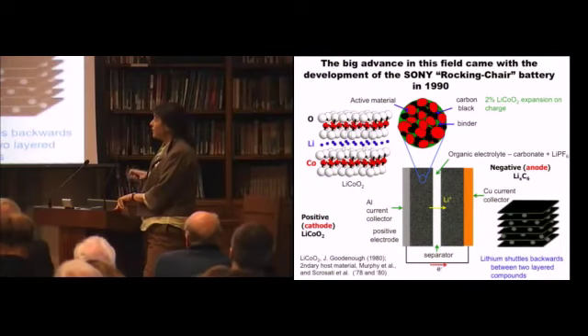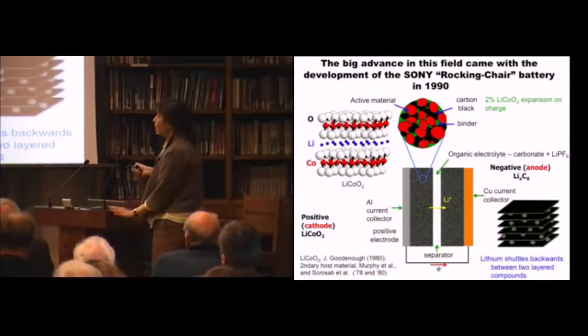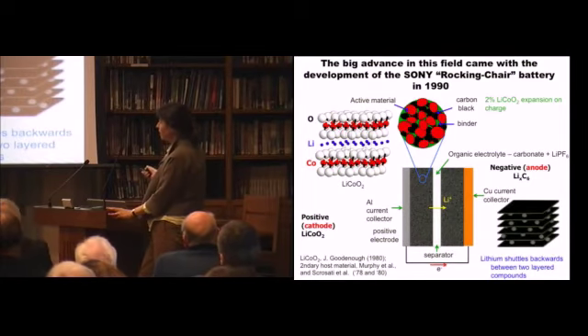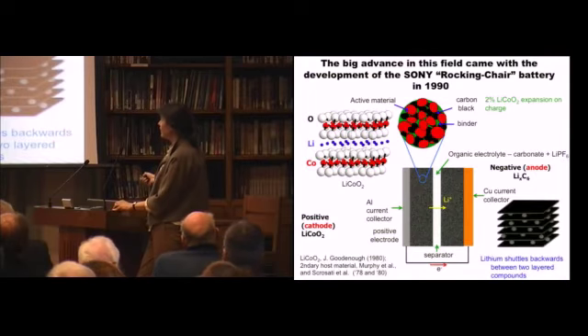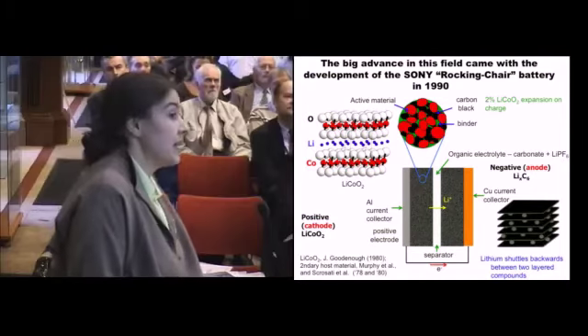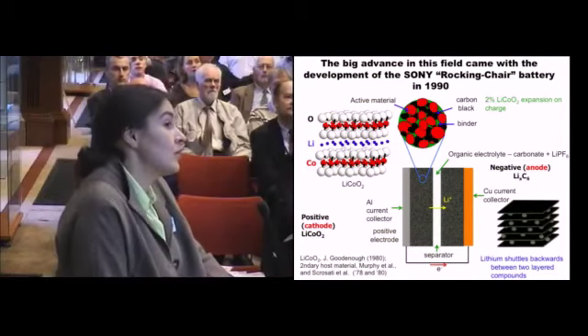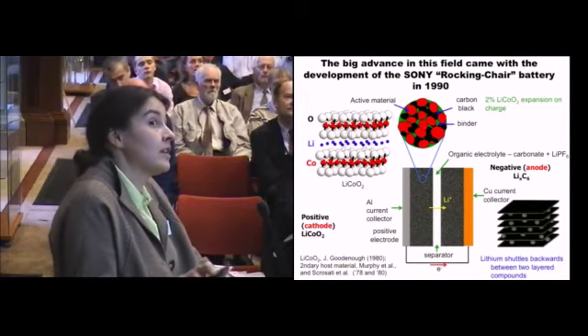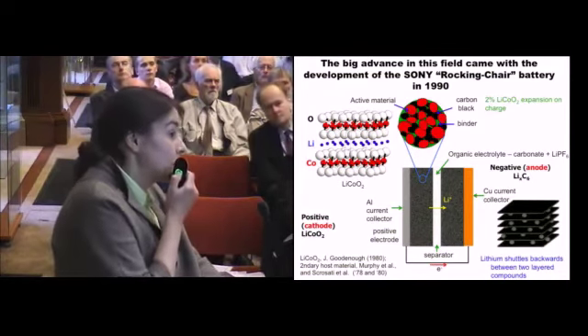And they put together this rocking chair battery with now, instead of lithium on the anode side, graphitic carbon. And so instead of plating lithium on a lithium anode, you intercalated, or inserted, the lithium safely into these layers. And so the lithiums now go backwards and forwards through this organic electrolyte, which allows lithium to be transported.